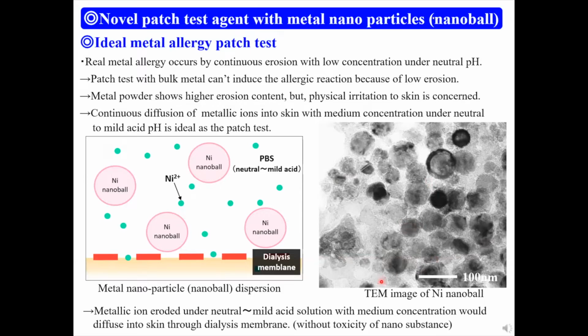In order to avoid direct contact of the nanoball with the skin surface, the nanoball suspension was applied to the skin via a dialysis membrane. With this method, only the eroded nickel ions would penetrate the membrane and be absorbed into the skin, but the nanoballs did not contact the skin. Therefore, the physical irritation of the nanoball can be avoided.